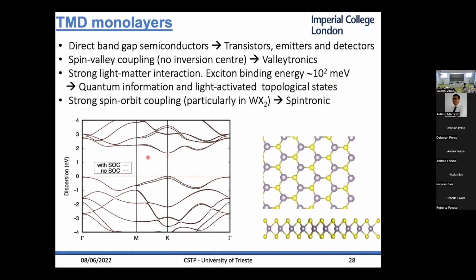Okay, so as an example, I'll show you the transition metal chalcogenides. The monolayers are already quite interesting materials. They have a direct band gap. They are direct band gap semiconductors. There's this strong spin valley coupling, so you have bands that are spin polarized at the K valley, and opposite spin polarization at K prime. And so you have strong light matter interaction as well, with exciton binding energy of 100 meV. And for some of the systems, particularly the ones that contain tungsten, you also have strong spin-orbit coupling. So the monolayers are already quite interesting materials.